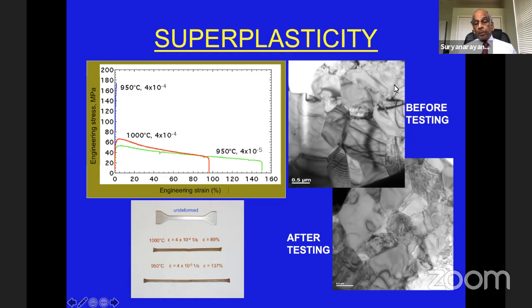For example, before testing, this is the type of microstructure, as I said, uniform distribution of the two phases and equiaxed. After deformation, after this superplastic testing, you can see the grain size is a little larger than here, but they're still equiaxed. That means the deformation is superplastic and not like elongation.